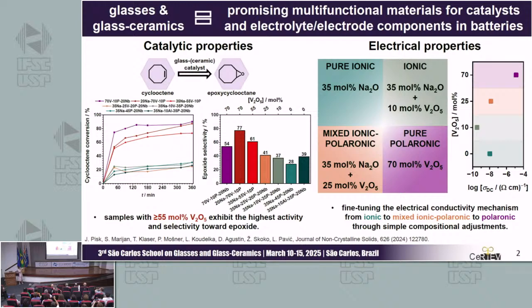So what we found out is actually that by simple changes in the composition, we can greatly improve both catalytic and electrical properties. And specifically, glasses containing higher amounts of vanadium pentoxide exhibit the greatest catalytic activity and selectivity. But also, it is interesting that exactly these glasses with a high amount of vanadium pentoxide also show the highest electrical conductivity. But what I will show you too is that by simple changes in the composition, we can fine-tune the mechanism of electrical conductivity from purely ionic to mixed ionic-polaronic to purely polaronic, just by simple changes in